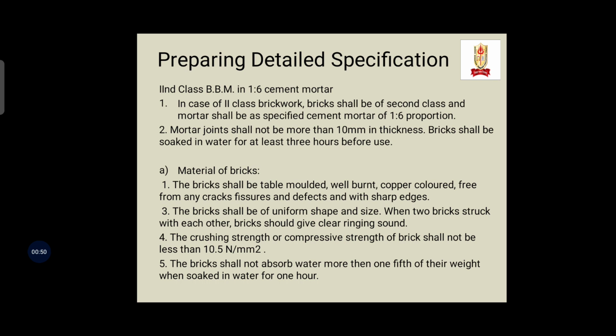So the brick shall be table molded, well burnt, copper colored, free from any cracks, fissures and defects, with sharp edges. The brick shall be of uniform shape and size. When two bricks are struck with each other, they should give a clear ringing sound. The crushing strength or compressive strength of brick shall not be less than 10.5 Newton per mm square. The brick shall not absorb water more than 1/5 of their weight when soaked in water for 1 hour.